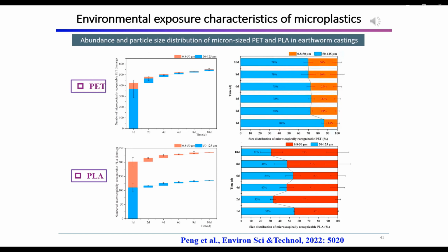During the 10 days of excretion, the proportion of smaller PET particles in PET microplastics separated from the cast increased from 14% on the first day to 30% on the 10th day. Differently, the smaller PLA particles in the cast of the first day accounted for 45% of the PLA microplastic, and the proportion further increased to about 70% on the 10th day. The digestive tract of the earthworms seemed to be more effective in breaking PLA polymers.